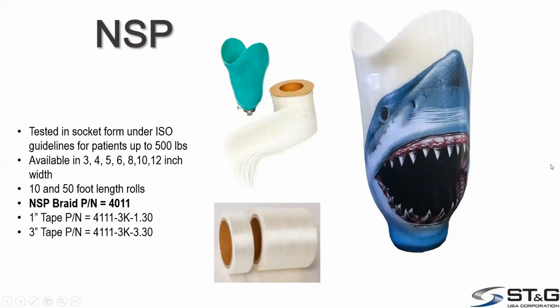NSP is available in different widths and different lengths, 10-foot and 50-foot rolls. It's also been tested under ISO standards for 500 pounds, but the results were inconclusive, and this is in regards to carbon, fiberglass, and the NSP. What had happened was the component that attached to the socket actually broke in many cases. So this is why we came up with a crush test to try to get some numbers that were more relevant and consistent.